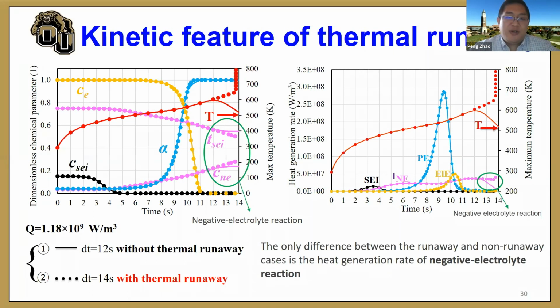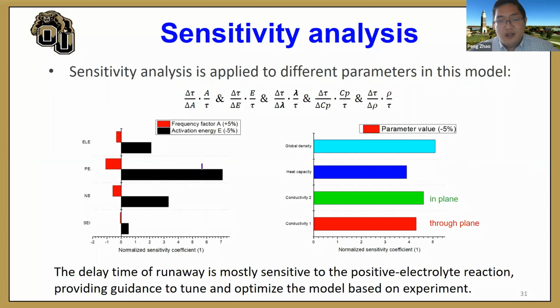So the first method is we trace the contribution of each heat source term from those 4 reactions. And we found that if you compare these 2 cases with the same heat source intensity but different duration time, one without thermal runaway, one with thermal runaway, you find that the negative electrode and electrolyte reaction has the strongest correlation with the thermal runaway. And also we can perform sensitivity analysis to understand what is the most important reaction that affects the delay time of thermal runaway. And we found that it's actually the positive electrode and electrolyte reaction. So these are all from the combustion methods.